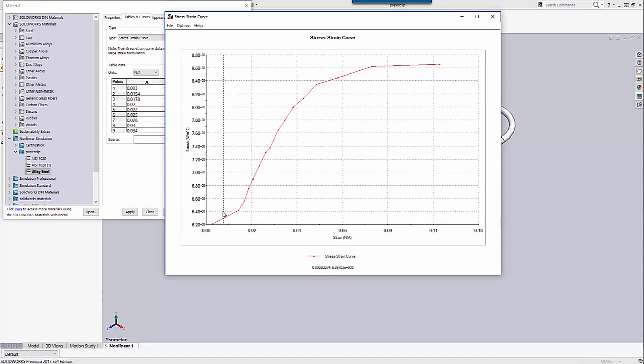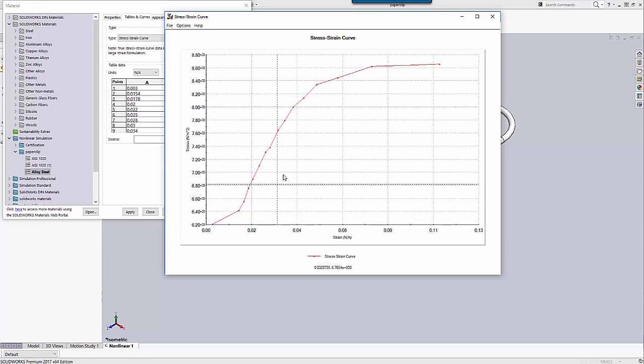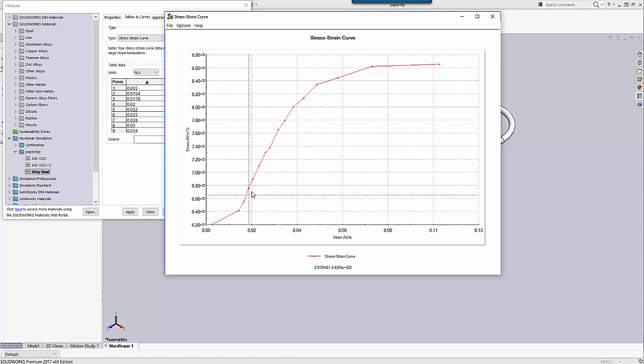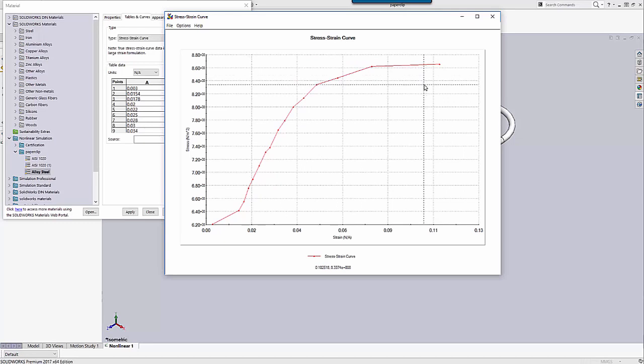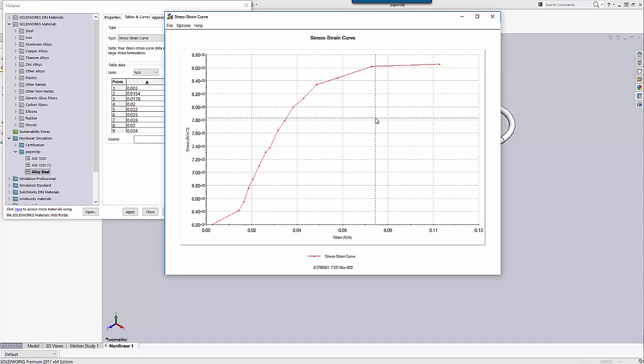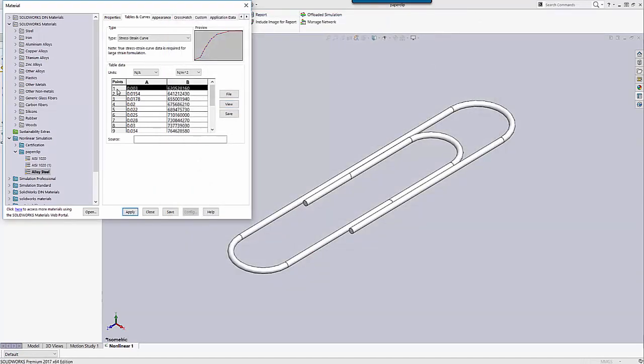The first mistake has to do with the very first data point. A lot of new users to SOLIDWORKS Nonlinear Simulation think this data point should be the very beginning of the stress strain curve — in other words, a row of zero strain and zero stress. But that's not the case. The zero-zero starts at the beginning of the elastic region. What this stress strain curve actually represents is the entire plastic region. So the very first data point needs to be the yield point of whatever material you're using, and all subsequent data points are in the plastic region. The program uses the elastic modulus to figure out the elastic region, so it just needs the plastic region from you.